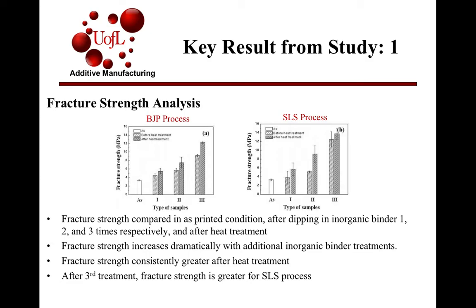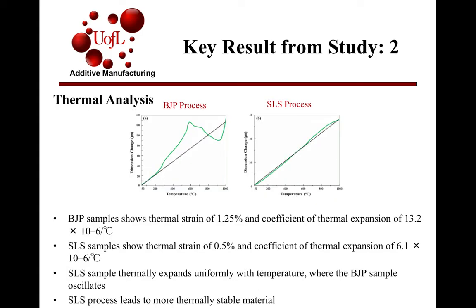The takeaways from this are that the fracture strength increases dramatically with the additional inorganic binder treatments. As you can see, there's a sharp increase from treatment 1 up to treatment 3. The fracture strength is consistently greater for post-heat treatment, and the final conclusion is that after all the treatments have been given to the material samples, the fracture strength is greater for the SLS process compared to the BJP process.